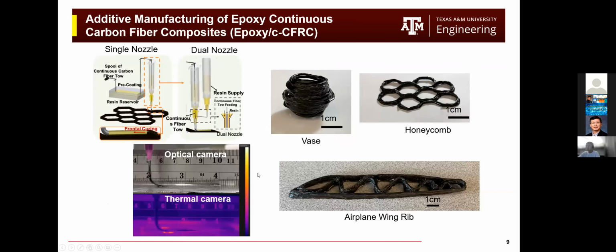So here we demonstrate some printed parts with the previously mentioned technology. We use a single nozzle design and a dual nozzle design to print continuous carbon fiber reinforced epoxy composites. By using these two different nozzle geometries, we were able to tune the fiber volume, so that the frontal curing temperature, the frontal curing speed, and the mechanical property can be tuned. Here are some of the parts we printed.